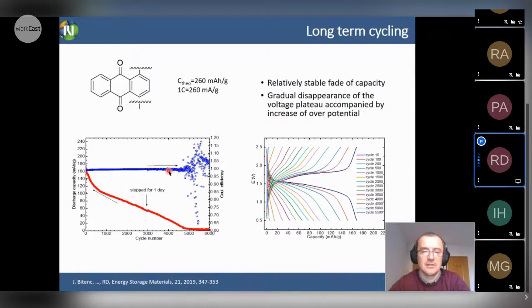And here, as I said at the beginning, we were able to cycle this polyanthraquinonyl polymer for several thousand cycles. In the first 500 cycles, we had a faster drop of capacity, but then this drop of capacity stabilized until all the magnesium was consumed completely. As you can see, the voltage plateau remained, but there was an increase, and the capacity fading is mainly connected with the dissolution of the polymer. And of course, here we also need to be careful with magnesium because magnesium was consumed.